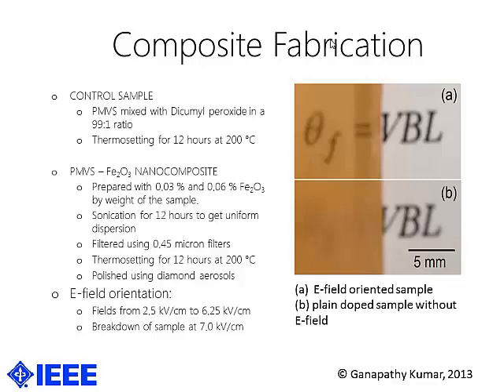Now, one thing that we did for this particular development was we used an electric field to orient the nanoparticles in the polymer before it was thermoset. That way, we wanted to test if there's some sort of a tuning in the optical clarity of the sample. The image on the side shows how an electric field oriented sample looks and how a plain doped sample without any sort of electric field orientation looks. Now, both those images are taken from a sample with the same concentration, the one above with an electric field orientation, the one below does not have one.